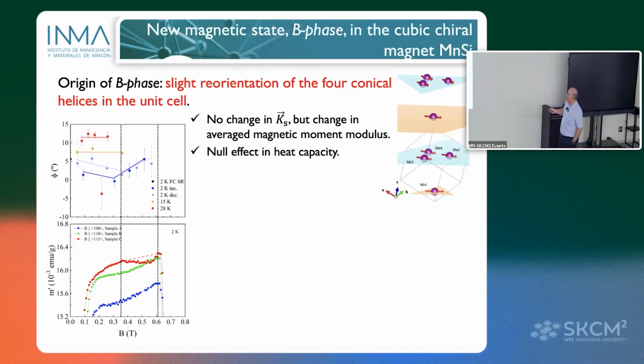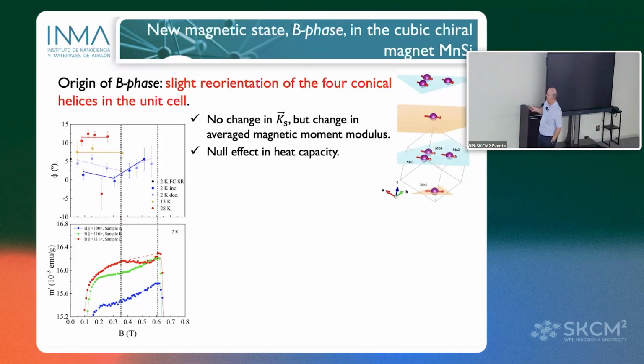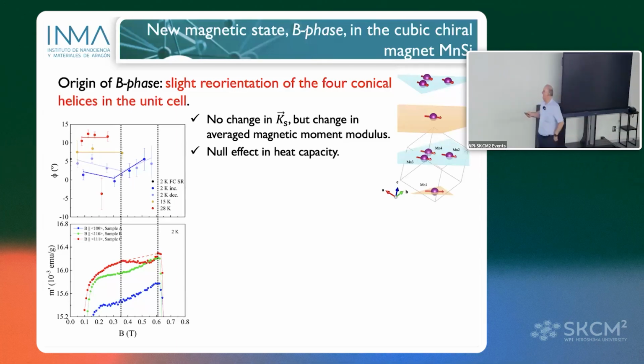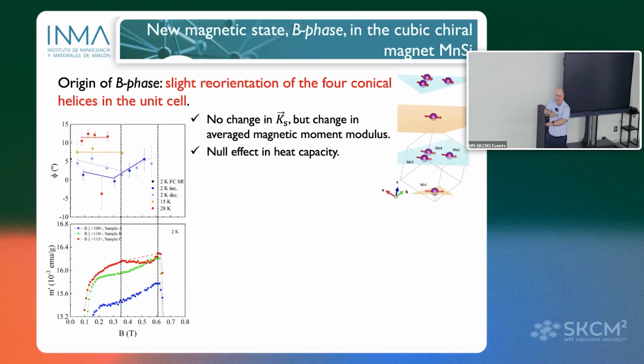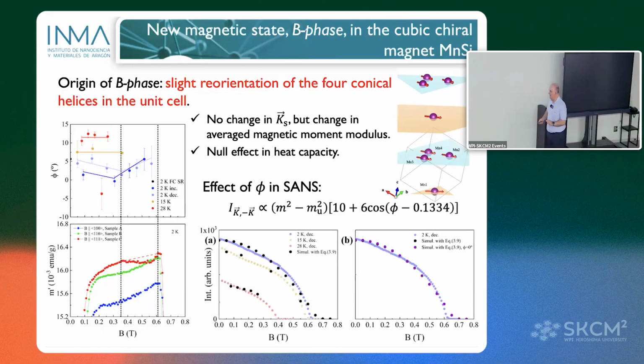And then you can see here the model: you have these layers, and along the 111 direction, the orange layers are forming a spiral with the same periodicity as the blue layers. And between the orange and blue there is a kind of shift. This model will be compatible with our SANS experiments, because the periodicity is the same, it doesn't change. All the helices propagate with the same periodicity, so for the SANS experiments, no problem.